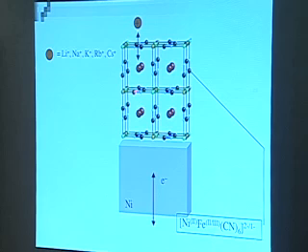And you have cyanide ligands hooking together, carbon on the iron side and nitrogen on the nickel side. And it makes this cubic lattice. And because those cyanides are negatively charged, there's a net excess of negative charge in that lattice, even with the nickel ions and the iron ions. And so there's some more cations, and they sit in this body-centered cubic position in this lattice. And they're whatever supporting electrolyte cations you happen to have around to do that.